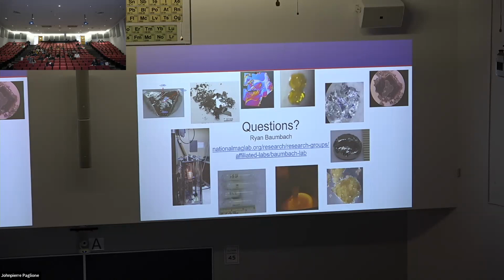And I think my advice, but it's probably nothing new to you, is that to try to get rid of inclusions, you have to try changing either the chemical composition profile to begin with, or the cooling profile. Right. And then it's really the hard work of trying it over and over again. Sometimes, by the way, that's possible. That's something you can do. Some labs do that all the time. Other times, if your elements are too expensive, you run into some pretty significant problems right away.